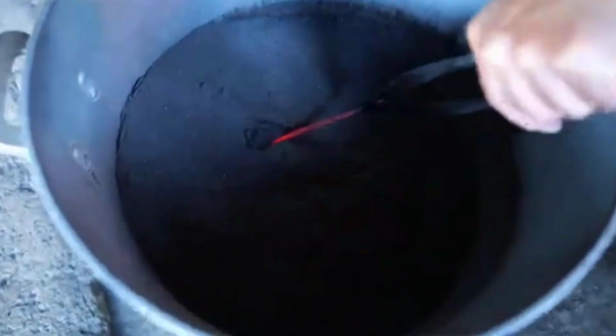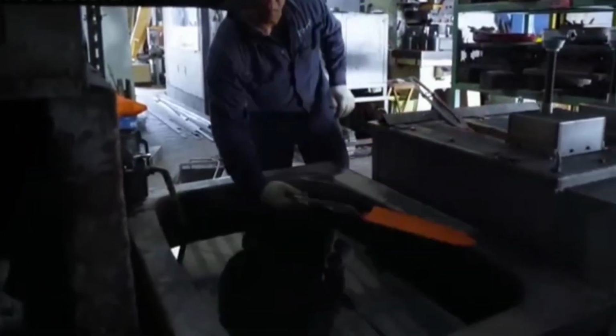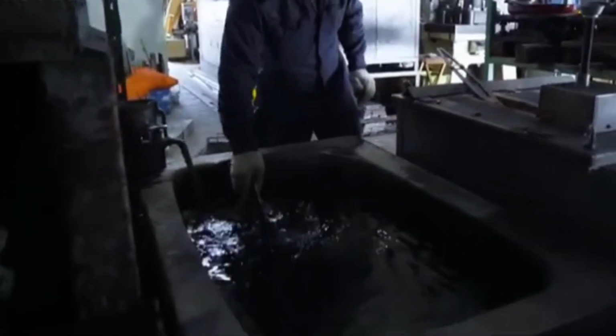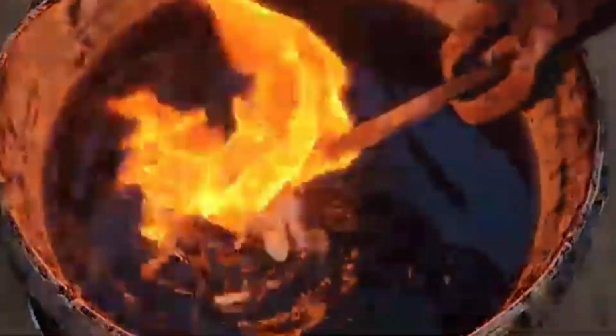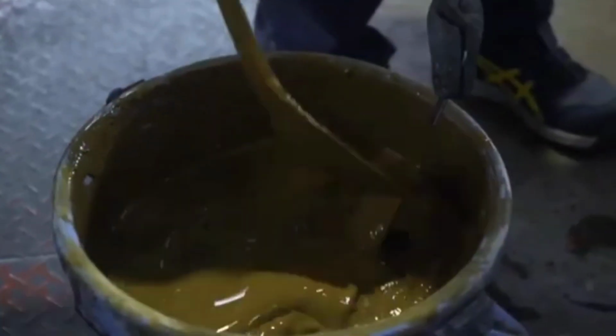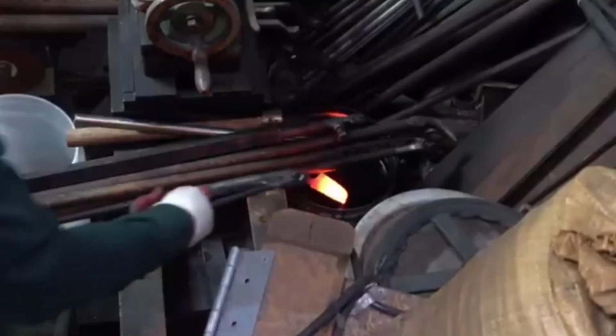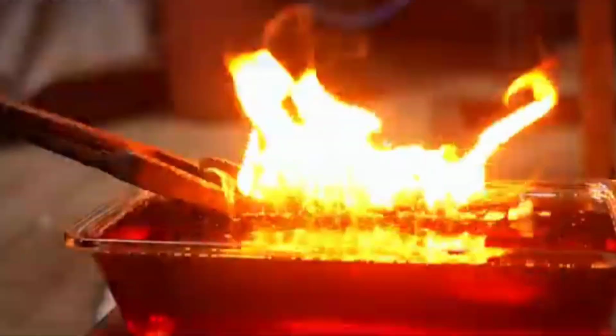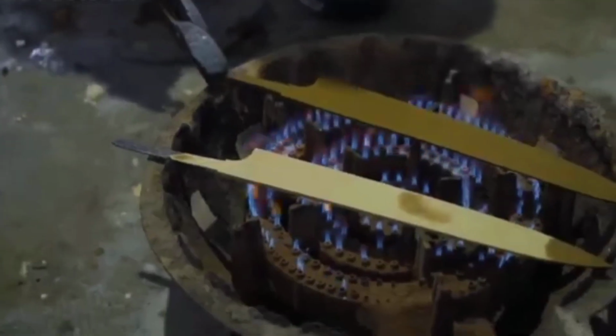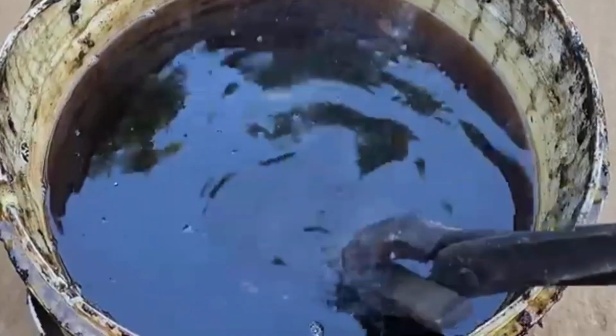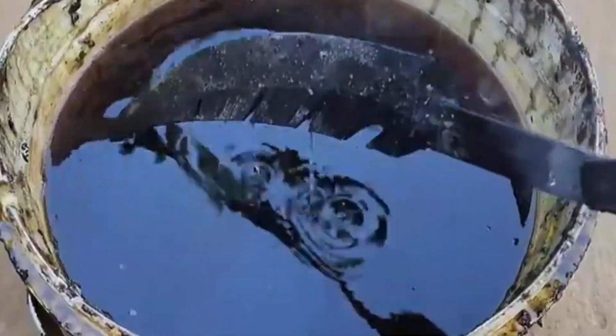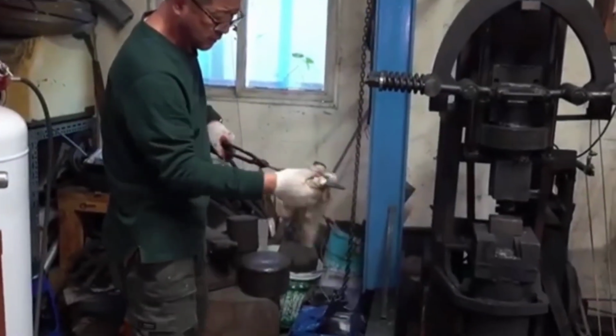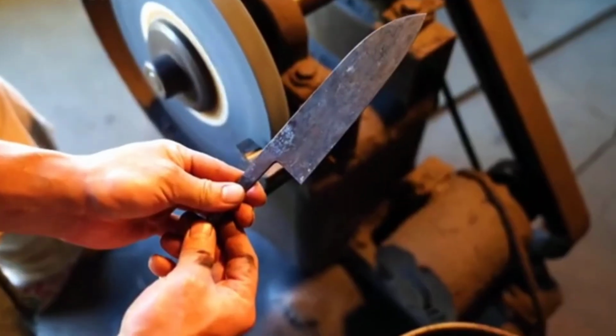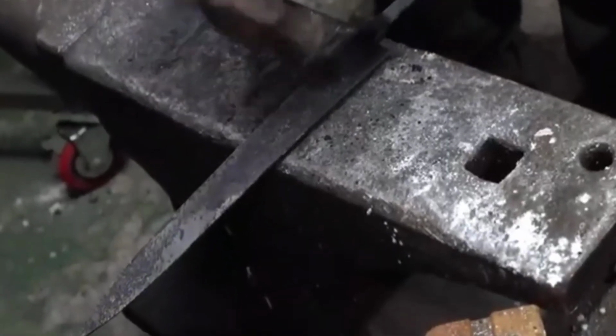Once the target temperature is reached, the blade is rapidly cooled by quenching it in oil or inert gas. This sudden change locks in the new crystalline structure, solidifying the steel into its hardened state. But the speed of cooling must be tightly controlled. Too fast and the blade could crack or warp. Too slow and the hardness won't meet the required standards. When performed correctly, this process brings the blade to a hardness rating between 60 and 62 on the Rockwell scale, ideal for professional-grade knives.